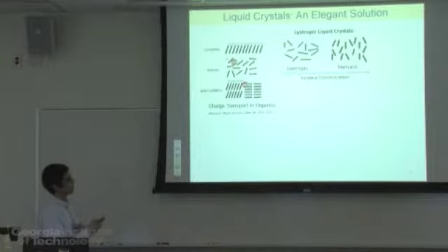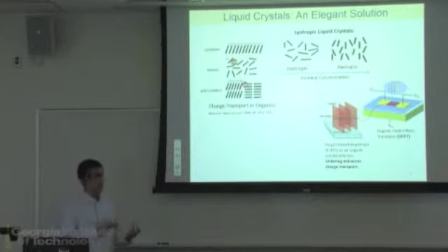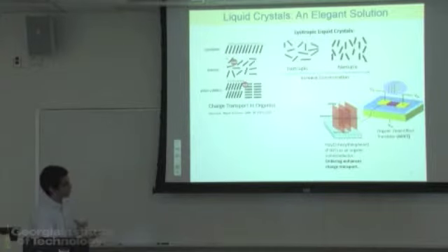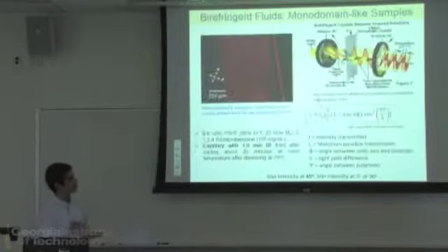And in a lyotropic liquid crystal, that can be achieved with an increase in the concentration of your material. So we're going to try to do this with P3HT, and if we can achieve these ordered materials, then we'll have improved performance in these OFETs, these transistors. That avoids the grain boundaries that you see in perfectly crystalline materials, but you still have this long-range ordering.